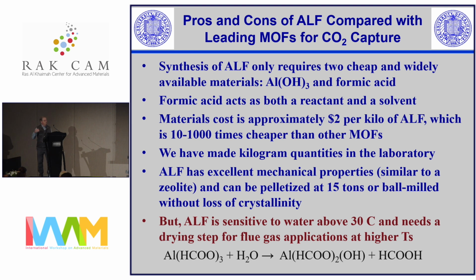The Achilles heel of ALF is that it's sensitive to water above about 30 degrees centigrade. So it needs a drying step for any process where there's heat and water involved. Either that, or you need to do something to it to make it hydrophobic.